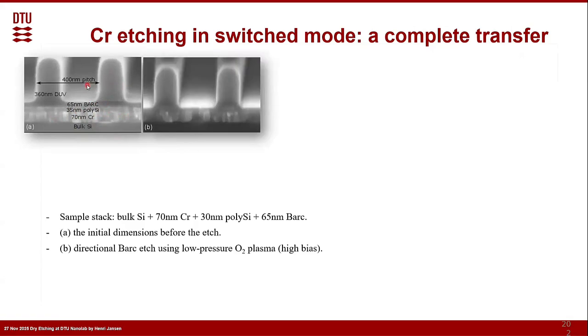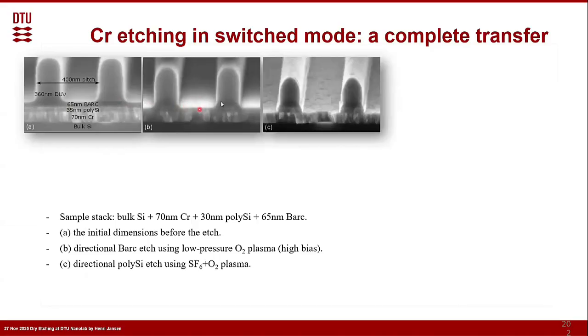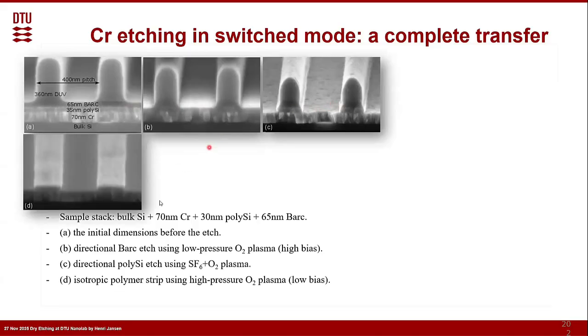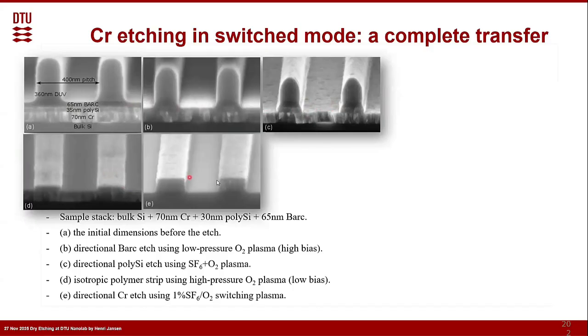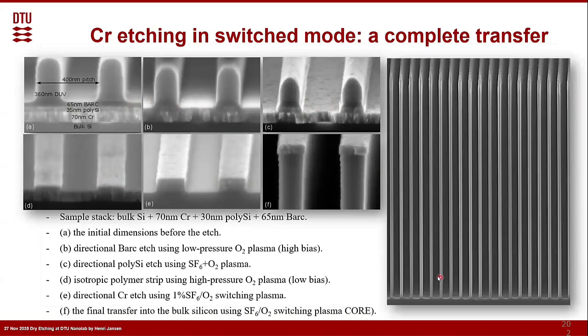So the first thing you have to do, and that can be done all in a single multi-step run in your reactor, is first you etch with a very low pressure of oxygen the bark layer, so that you are opening up the polysilicon. Then again, with a very low pressure, you use, let's say, a continuous mode of SF6 plus oxygen to etch away the polysilicon. Then you can strip the photoresist. We don't want to have it anymore. And then we use the polysilicon as a mask to etch the chromium. And after we have done that, we can etch with the switching process inside the silicon which is beneath it.